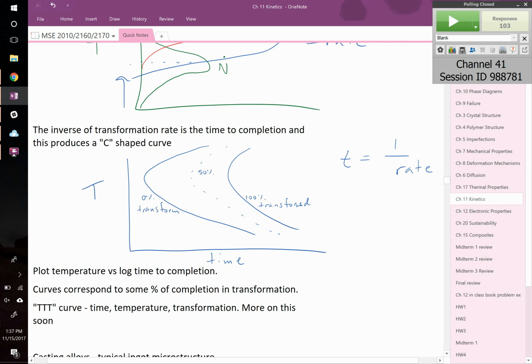So what this shows you is, let's say that you could somehow magically change the temperature of your alloy instantaneously. We'll learn later that that's not possible. It always takes some amount of time to change its temperature. But if you could, let's say the transformation temperature is up there somewhere, but you instantly bring it down to this temperature, you could wait some period of time before any transformation occurs, right? But as soon as you touch the nose of that TTT diagram, that's when your first transformation starts to take place. And then the longer you hold it there, by the time you get to this time, whatever that is, your transformation is going to be complete. This is typically plotted on a log scale, so this is log of time down there.